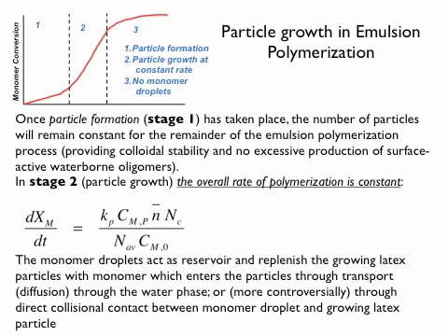And if we think that monomer gets consumed, obviously because monomer conversion goes up, then this is a little bit counterintuitive in the first instance. Because if you look at bulk kinetics, you would get the rate coefficient of propagation times monomer concentration times radical concentration. If radical concentration is assumed to be constant, so you have a constant flux of radicals, then monomer concentration in a bulk polymerization would drop, which means the rate should drop. And in this particular case, the rate stays constant.